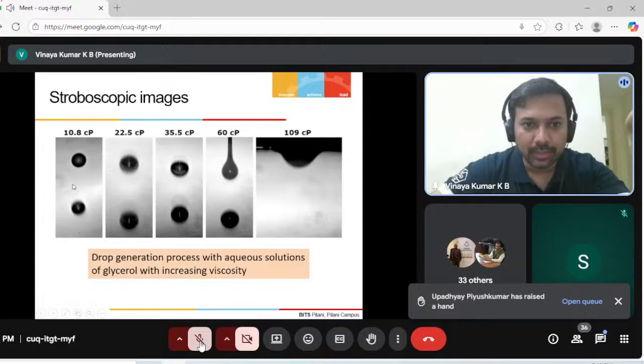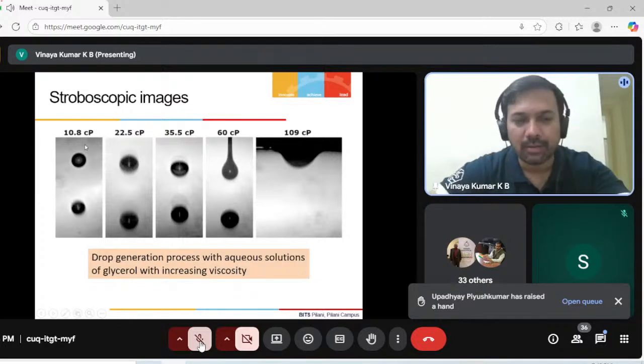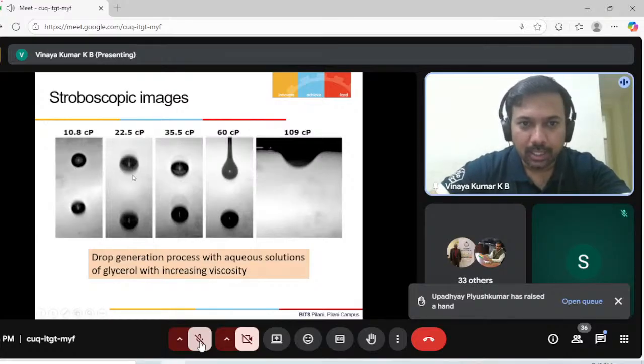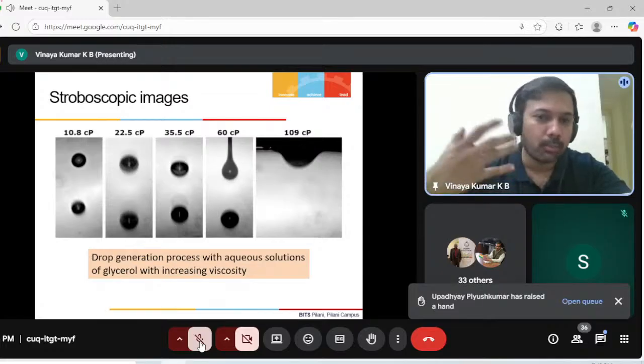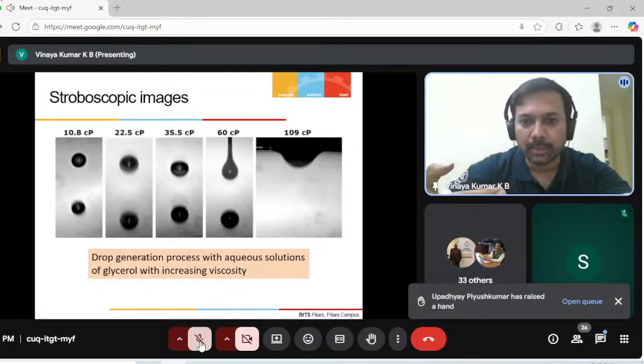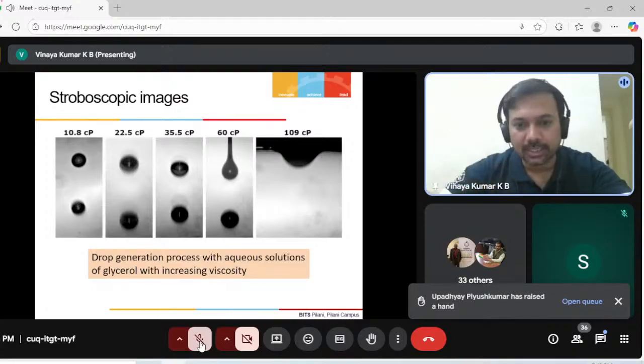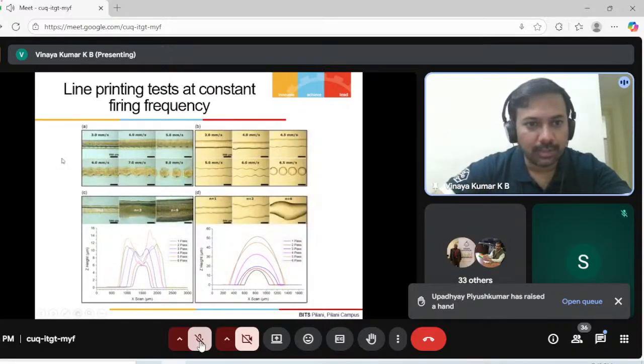Also, normally in current inkjet printers, the viscosity should be less than 10 cP, like 7, 8, or 5 cP. These viscosities are very good to generate the drops. Where we redesigned the print head, we were able to print viscosities as big as 60 cP. In this way, we are able to accommodate more functional inks, even nanomaterial based inks, and print different sensors from here.